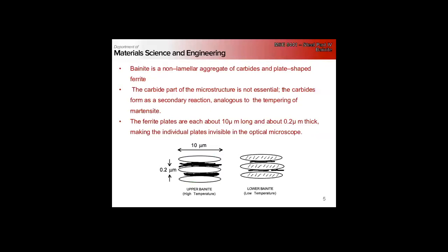And we can actually alloy with certain element combinations which will suppress the carbide formation. And so we can have Bainite that's composed of supersaturated ferrite, right? Much like making it even more like martensite.